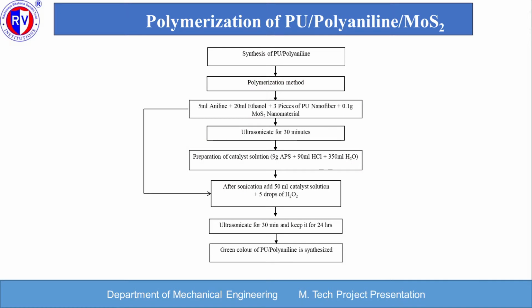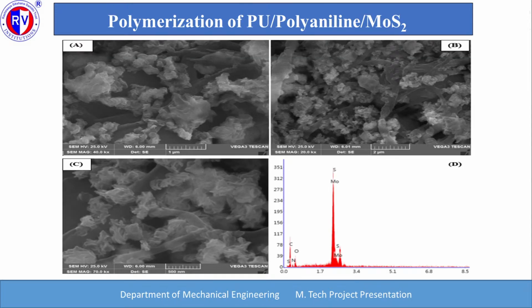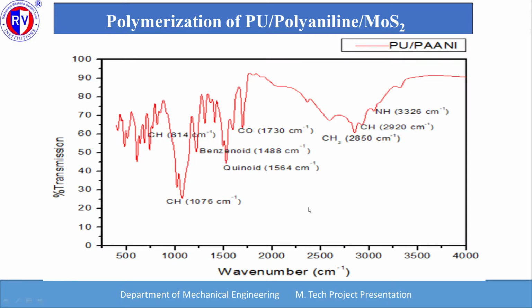And further we have polymerized PU, polyaniline, and MoS2 combined. This is the procedure we have followed, and these are the SEM images. Here you can see that on the fiber it is clearly visible that the MoS2 is very well coated on the fibers. As you can see here, it is very well coated, so it will be very good for the purpose of electrochemical sensing. As you can see here in the EDAX, it shows molybdenum, sulfur, carbon, oxygen, and nitrogen. And this is the FTIR that shows the crystallinity and the bonding.